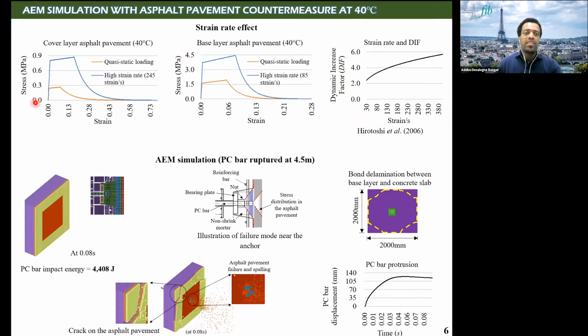So in the numerical simulation at 40 degrees centigrade for the cover layer, this is the material behavior at quasi-static loading, which is obtained from the bending experiment, which I already explained. But when the bar is impacting the asphalt pavement, its behavior is something like this. It is highly enhanced. This one is for the base layer. The orange one is at quasi-static loading, and the blue one is at high loading rate.